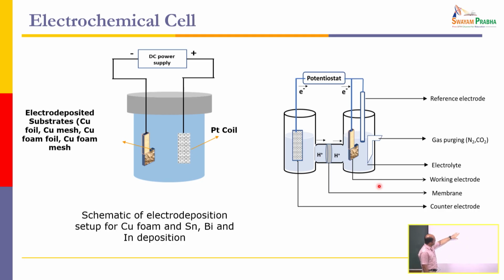So we wanted to get into a liquid product, where we had a copper mesh. A similar copper mesh was taken, and this is a process in which we made this copper into a copper foam. So you have a flat surface of copper that is made into copper foam, and over which we then deposit a catalyst. A catalyst like tin, bismuth and indium were deposited on this. All this was done in an electrochemical process. There is no high temperature, no high pressure, it's all done at ambient condition. You have an aqueous solution where these precursors are dissolved. You apply a current or a potential where you can deposit these metals onto this substrate, and that is then used as an electrode for CO2 reduction.